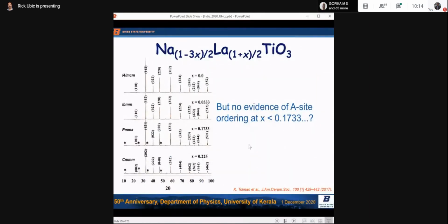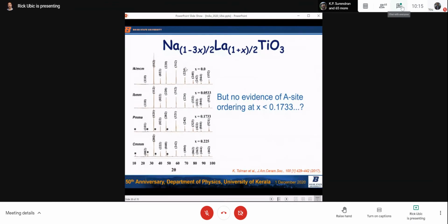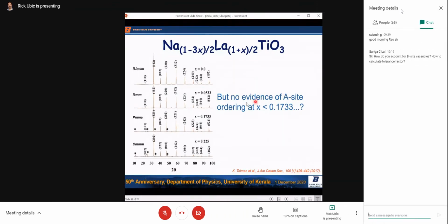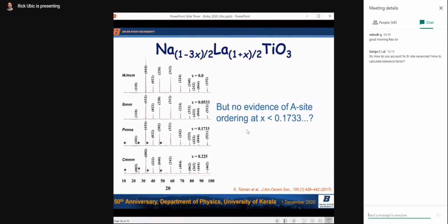And the funny thing here is that this is our X-ray data, and this is why people publish this as disordered. This is sodium lanthanum titanate, X equals 0, the stoichiometric composition. There are no ordering peaks here. There are no ordering peaks here. They don't appear until X equals 0.1733. They start to appear. So the question this raises is why is there no evidence of ordering when there should be ordering, right? You'd expect ordering to be best when you're nearest the ordered stoichiometry, a one-to-one stoichiometry, and worse as you go away from it. But that's not what we were finding until you look. What we're seeing here, it's not no evidence of A-site ordering. What X-ray is showing us is there's no evidence of long-range A-site ordering, right, at those low X values.